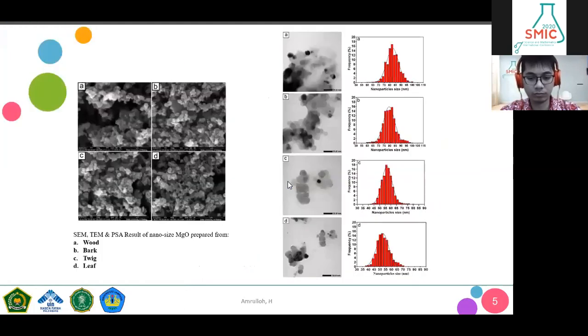This is the result of scanning electron microscopy, transmission electron microscopy, and particle size analyzer. This figure shows that the resulting magnesium oxide nanoparticles are in the form of spherical. The result of the particle size analysis shows that magnesium oxide with a particle size in the nanometer range, with relatively narrow distribution, was produced from the application of the four plant extracts.